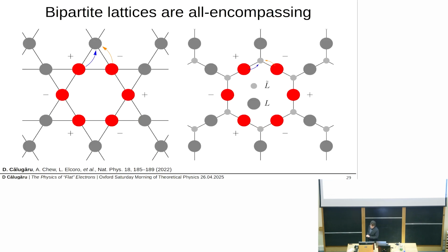And you can even show that the Kagome model I showed previously is actually included within this formalism, and I'm showing here in this slide why that is the case. If you take the Kagome lattice and call that your big sublattice, and put a virtual honeycomb lattice, you can see that the same wave function for the flat band in the Kagome case is a wave function of the flat band in the bipartite crystalline lattice case.